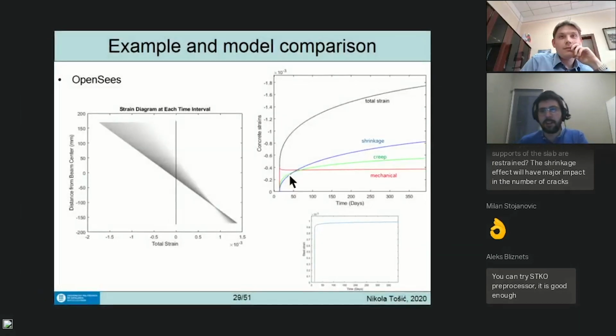So what this model will allow you is to plot interesting things such as the distribution of strains across the cross-section height in time. And this is what you saw in the earlier image. We are starting from a line that is here and basically rotating around the reinforcement or slightly above it and having an increase in strain at the top fiber over time. And what else? A decrease of the neutral axis. What else can you see? As I said, the strain does not change much. It's a very small image. Probably you don't see it very well here, but it's almost constant.